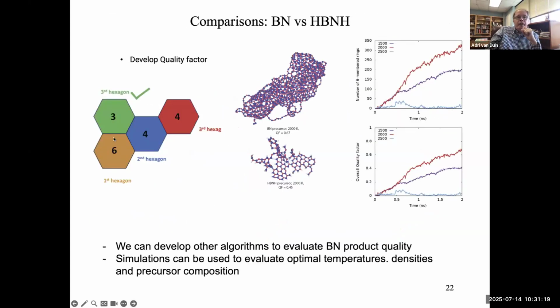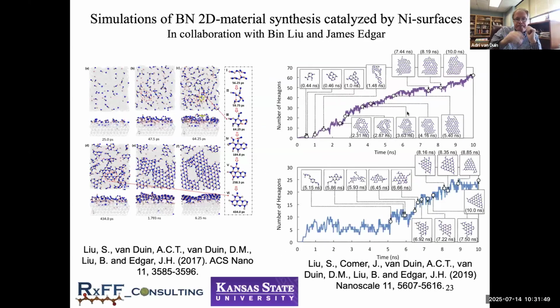And then you can do all sorts of fancy analysis. We can, for example, look at how rings connect to one another. So we can look at the quality, we can develop quality factors. So if you want to have a 2D material, we can develop a quality factor that indicates that. And then very quickly, we can figure out what is the right temperature. So we can see here, for example, 1500 Kelvin gives reasonable growth. 2000 Kelvin gives better quality. 2500 Kelvin really is too high. Now we really lose control of the quality of our structure. And that's nice information for the experimentalists to work with.